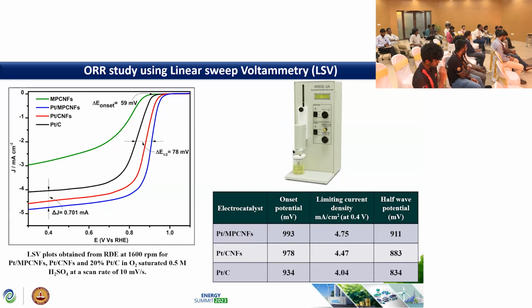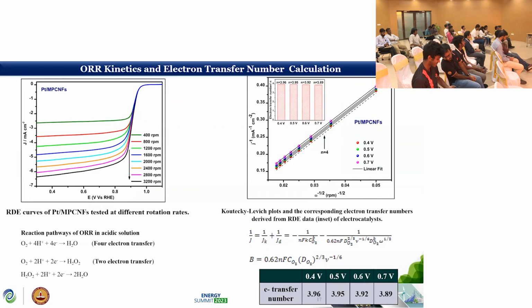We also could see that the limiting current density has increased in the case of these mesoporous carbon nanofibers. And to understand the ORR kinetics and electron transfer number, again we conducted LSV under different rotation rates using RDE. We also attempted KL plots to calculate the electron transfer number using the KL equation. We could see nice linearity and parallelism, and from the slope and intercept we calculated the electron transfer number, which was found to be approximately 4. That indicated that the reaction pathway of ORR in acidic solution was following a 4 electron pathway.